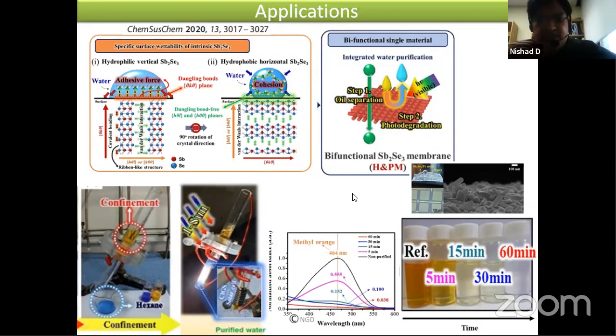So this paper deals with antimony selenide. So we tried another material. Now this antimony selenide has a very low band gap, almost very lower than bismuth vanadate. And now again we try to control the facets here. You can see the 0k0 surface, which is having covalent bonding along this direction, and the facet H0L or H00 having a van der Waals bonding structure along this direction.